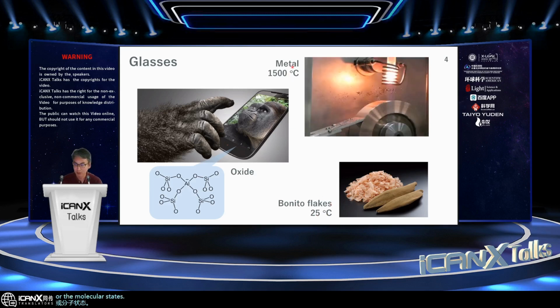In the case of metal, of course, usually the metal prefers to form a crystal. But if we do very fast quenching, cooling from the liquid state to the solid state, we can sometimes get metastable states, which correspond to metallic glass. This is an example of a copper-based metallic glass. You can see that this melt is going down so quickly that it is quenched to form the metallic glass. You can also take a look at these bonito flakes.